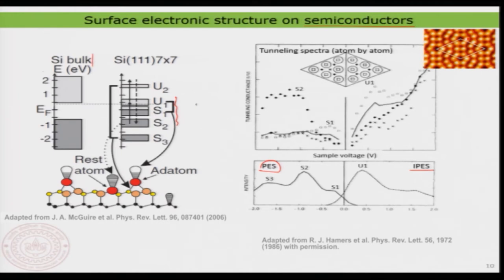That's just the opposite of photoelectron spectroscopy, but just keep in mind that when I measure the photoelectron spectroscopy, you clearly see that I can measure the S1 and S2. So these do correspond to each other. Although the UPS is actually a bulk measurement, I can still see that these surface states are present, and therefore I can clearly measure that. The only difference is the broadening. Of course, I can see the signature appearing more like a shoulder, but it is broader than what you measure in the scanning tunneling spectroscopy. But nonetheless, we can measure that. Similarly, the U1 is also present here.